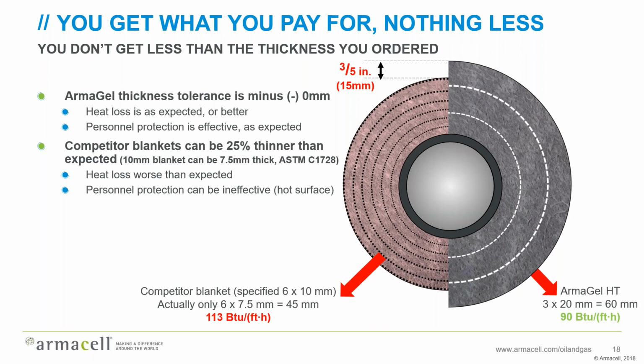But there's something in the ASTM that not a lot of people have caught sight of. It gives a tolerance of plus or minus 25% allowable on blanket thickness. So in other words, if you put 6 layers of a 10mm blanket around that pipe, you would expect that you'd get 60mm total thickness. In reality, if you're at the lower end of that acceptable thickness range, you could have 15mm less, or 3/5 of an inch less on the overall thickness.